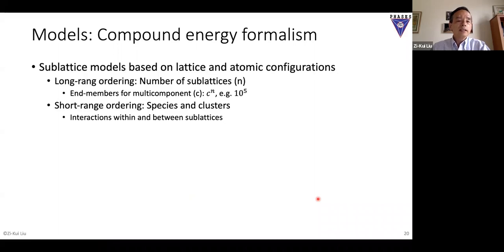Okay, so models - model is key, right? Without good models, it's not going to work well. So the sublattice model is based on lattice atomic configuration, as I mentioned. So you have long range ordering that gives you the different sublattice positions, and you have short range ordering because of atomic interactions.